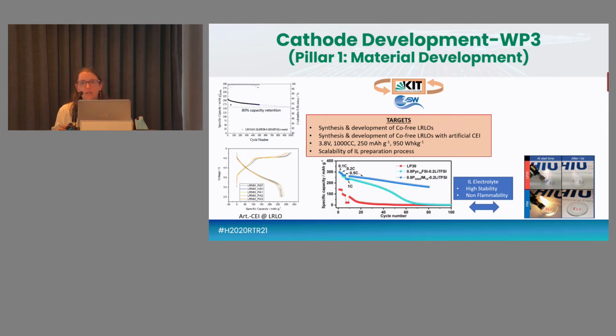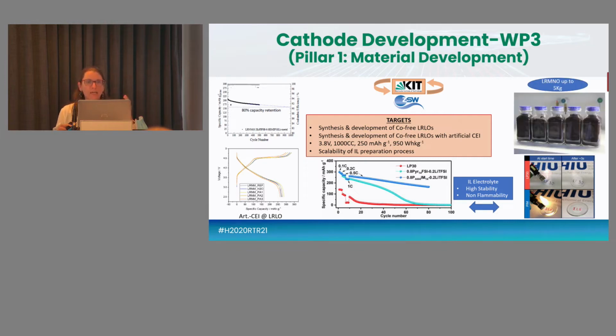This kind of ionic liquid electrolyte, as the graph in the center shows, is showing outstanding performance compared to the standard electrolyte, the carbonate-based one in red. And the most important aspect for us in using this ionic liquid electrolyte is to avoid any kind of flammability of the cell, and we demonstrated that this is possible. Again, always keeping a focus on the upscalability of our material.